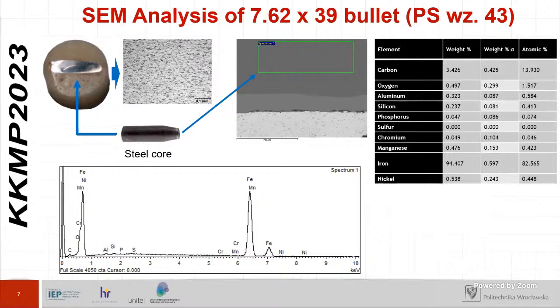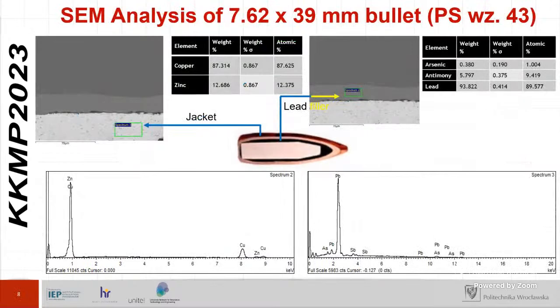And you can see from here, from the percentage of the weight of each chemical composition, the proportion of iron is about 94%. So definitely this is a steel core, right? And from the next slide, you can see the lead filler, which is the second layer that follows the core, depending on the direction you are viewing. If you view from above, it means next to the jacket. And if you view from inside, it's next to the core. So we have the lead filler here, and you can tell from the proportion or the amount here, which is about 93.8%.